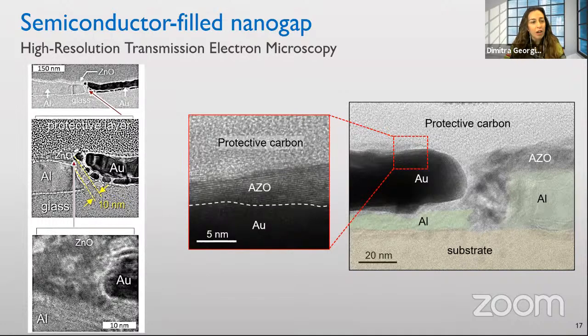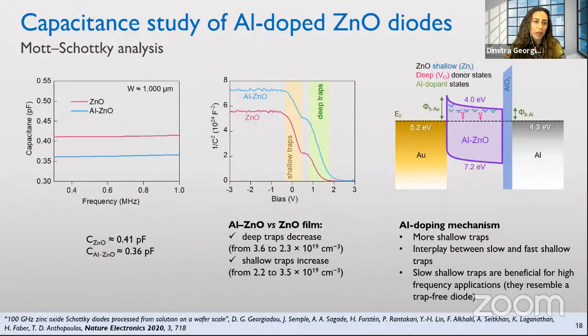And to prove that, we had again to go to high-resolution transmission electron microscopy, which we performed along with our collaborators in KAUST in Saudi Arabia. And we saw that both zinc oxide as well as the aluminum-doped zinc oxide fills the gap, and it's not only covering, let's say, the top of the electrode. So we were certain that the performance we could see, the electrical performance, was due to this material we fabricated.